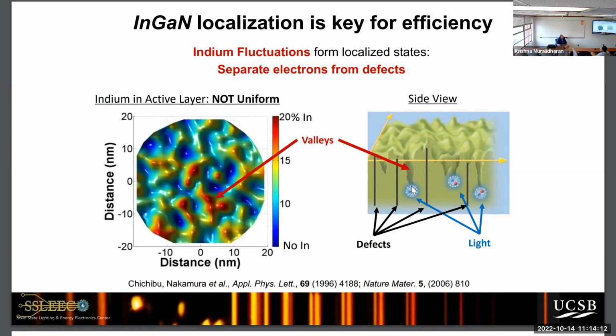So the electron hole recombine here, and that keeps them away from the defects in the crystal. My colleague who got the Nobel Prize says they didn't know this was happening. This was all found out after the fact.